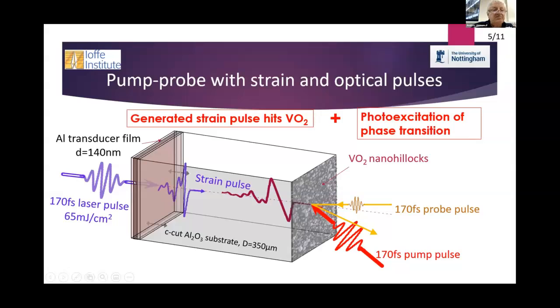It is in the same way how I showed you in the first slides, and then the strain pulse is injected. It is propagating through the sample, and then it affects vanadium dioxide film, where the phase transition is excited by this red line.